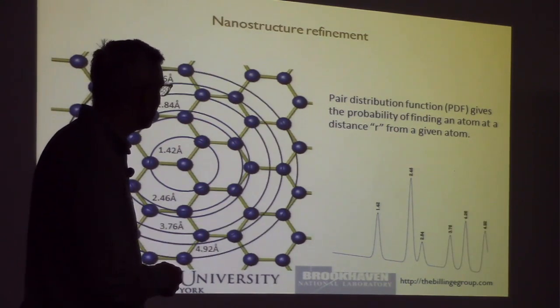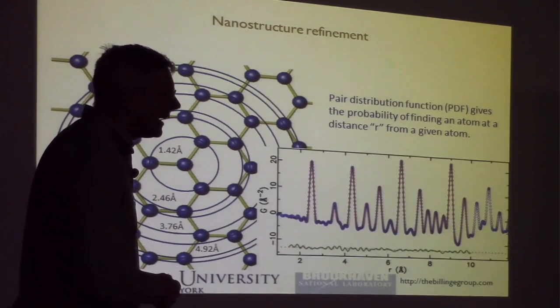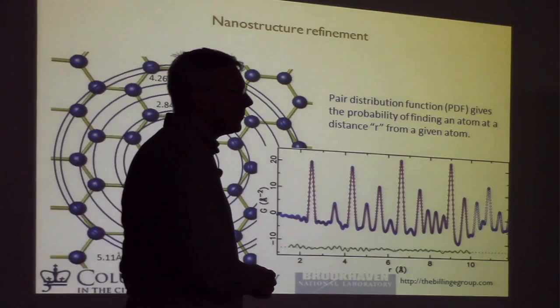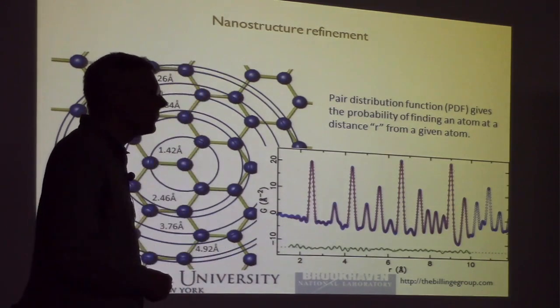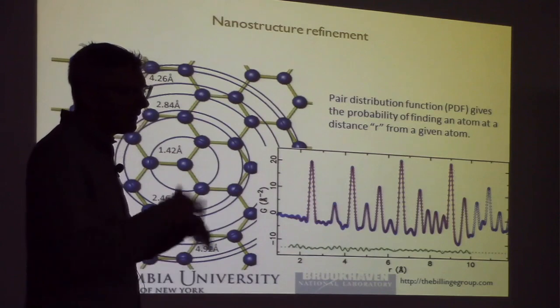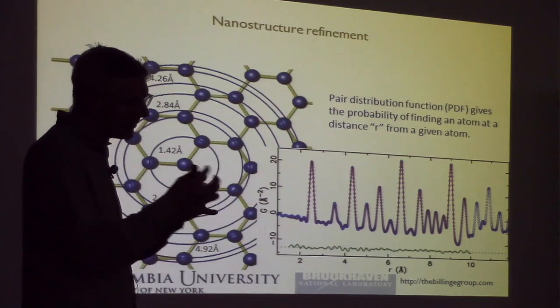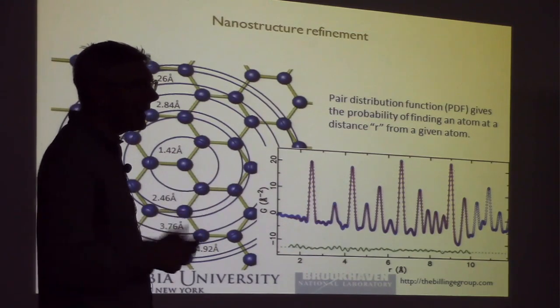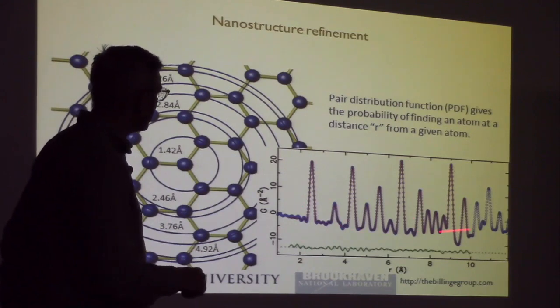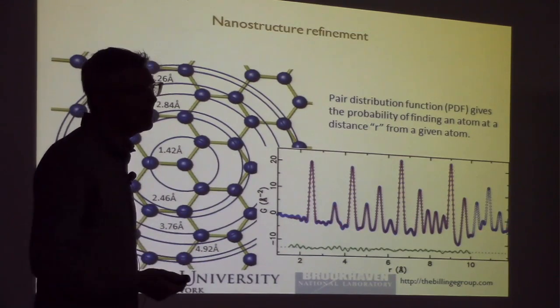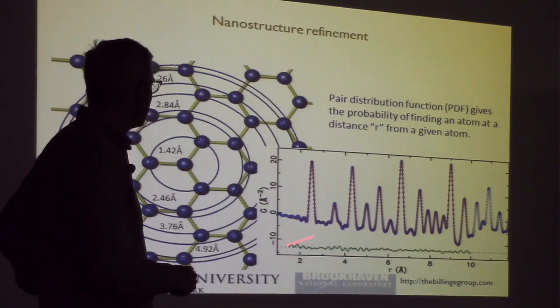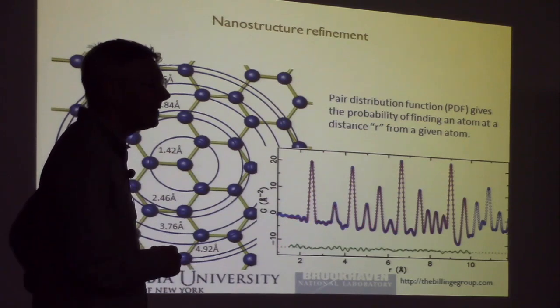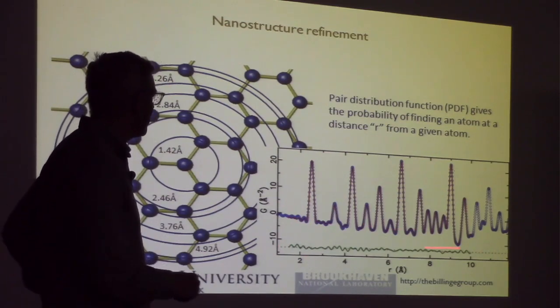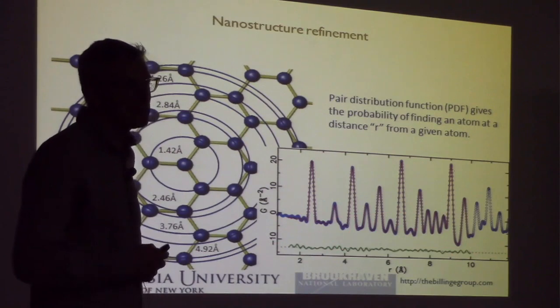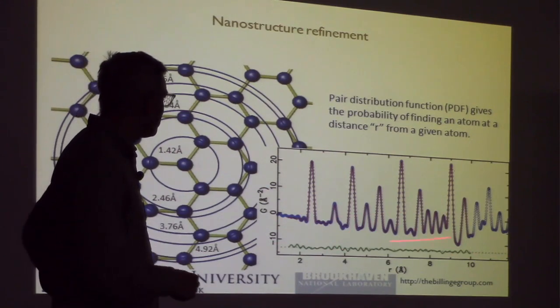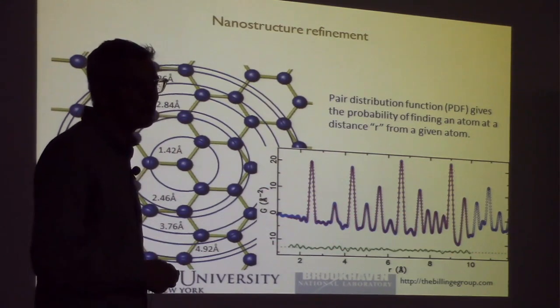And we place peaks at those positions. And now we have software programs that will do this for you, and they'll also do regression. So that means that they'll do fitting, and they'll move the atoms around in the model in such a way until you get a good agreement. So here the blue curve is a measured PDF of nickel, and the red curve is a calculated PDF of nickel, and the green curve is the difference. And we can get actually very good fits to well-known crystal structures.